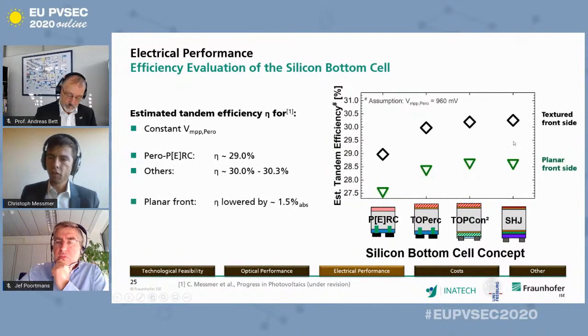We can not only do this for a textured front side, but also for planar front side, where we see that the efficiency is lowered by 1.5% roughly in absolute efficiency. And we can also do this for the different interconnection layers and for monofacial devices, but I do not show this here, but I refer to our paper, which will come up soon.